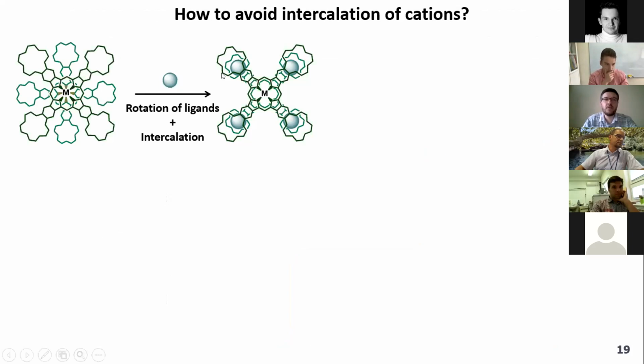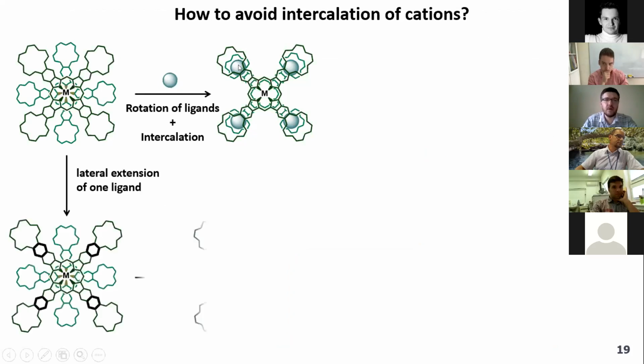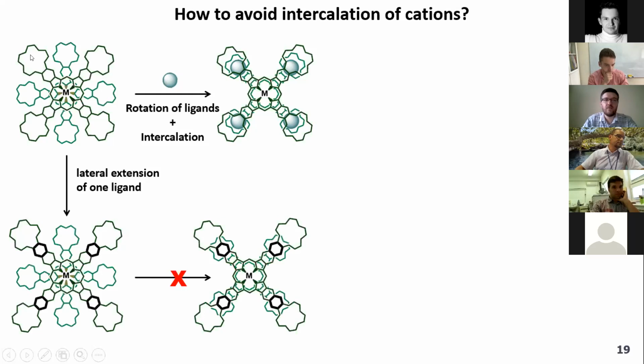So we know that intercalation occurs when molecules adopt eclipsed conformations, and thus crown ether rings overlap, and potassium ions can fit into these positions. So what we decided to do is extend one of the ligands by addition of more rings, so that even in eclipsed conformation, crown ethers cannot overlap.